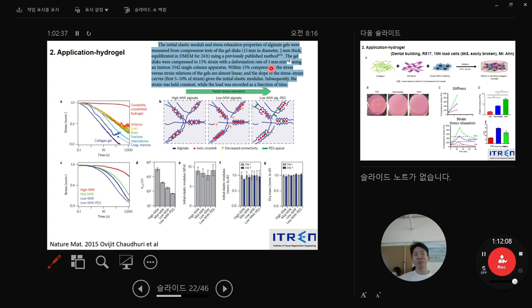So for example, as a tip, if you want to highlight your material, to say our material has very high stiffness and high strength, you can make this rate higher, and then you can get a higher value. I used an Instron machine and a single column apparatus. The single column apparatus is a flat apparatus, and within 15% compression, after this 2 millimeter thickness becomes 1.7 millimeter, the stress versus strain ratio of the gel is almost linear, and the slope of the stress strain curve gives the modulus. So the stress strain relation is almost linear. What is the meaning? Their behavior is quite elastic.